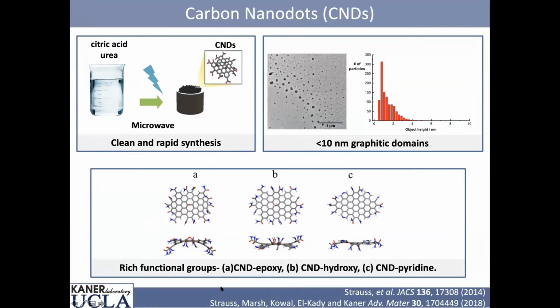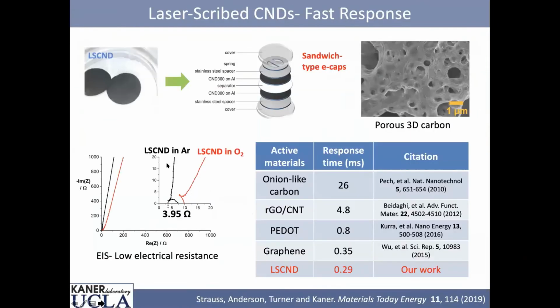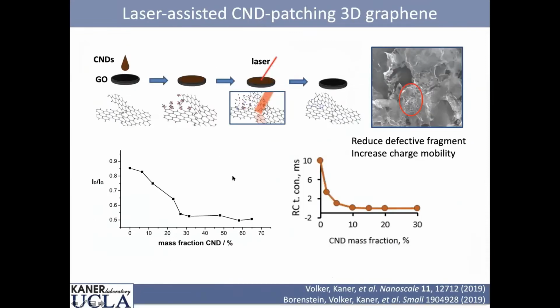We published a paper a couple of years ago in Advanced Materials. It's been a very highly cited paper. People are interested in these carbon nanodots. But what we're interested in using them for is to repair graphene. And we've shown that these materials now are down at 0.29 milliseconds. Let me show you this.